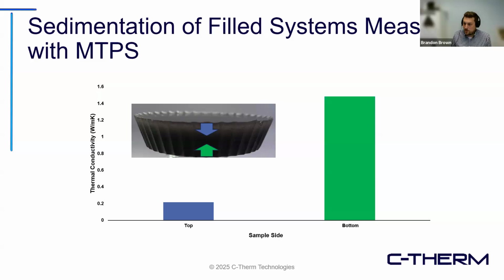We had one client who had two groups within the same organization, the R&D and the production teams, where the R&D group was telling the production team the QC samples were passing, and the production team was telling the R&D group that they were seeing material failures. The root cause was later determined to be that settling had occurred, which was only possible to see using our MTPS single-sided transient technique, where we measured each side separately. And in this case, you can see there's an order of magnitude difference in performance just due to settling during curing. Next slide, please.